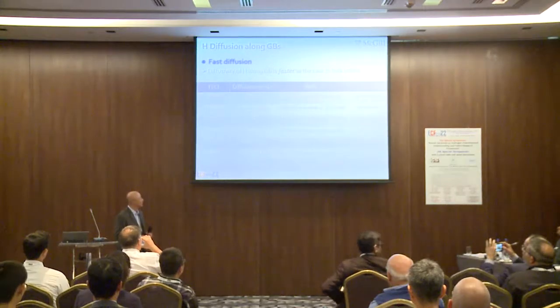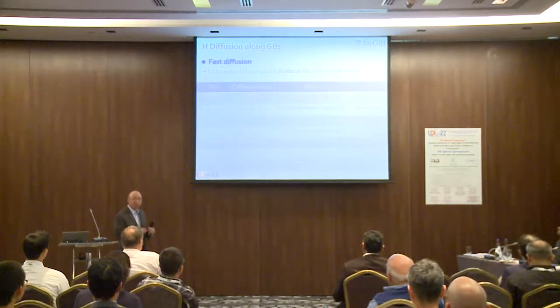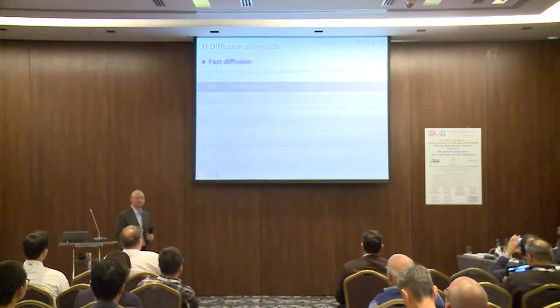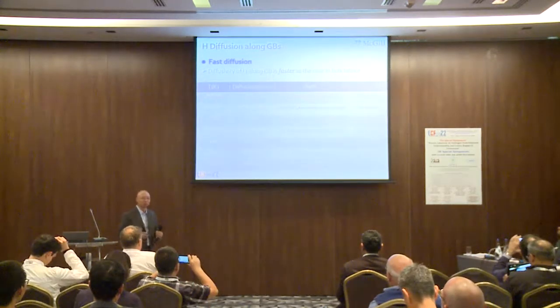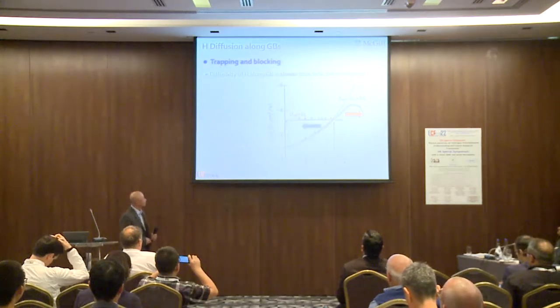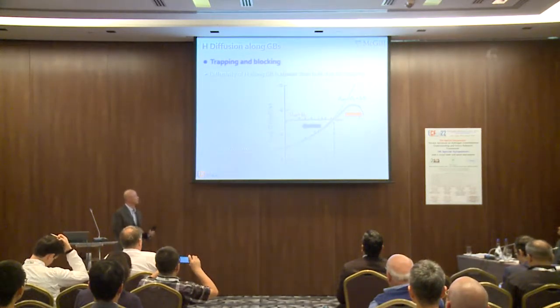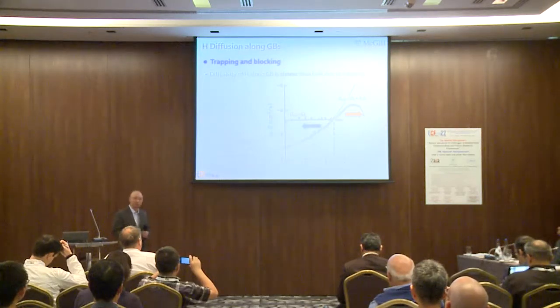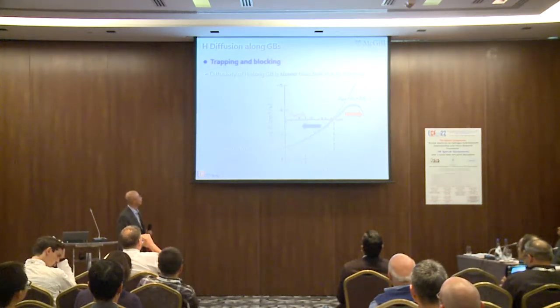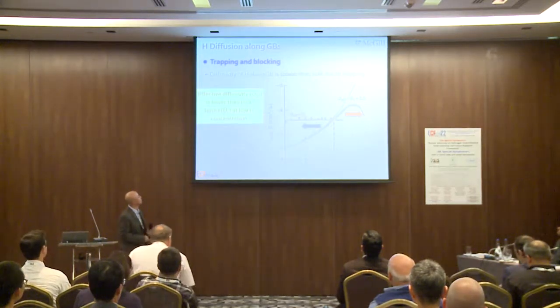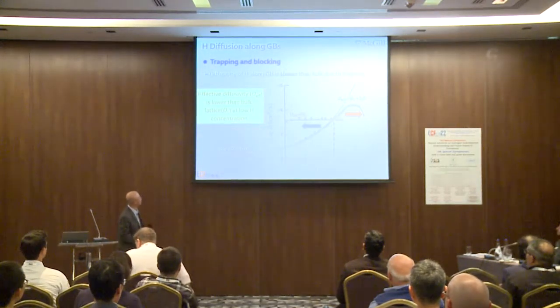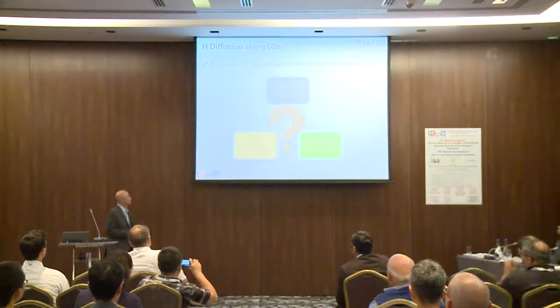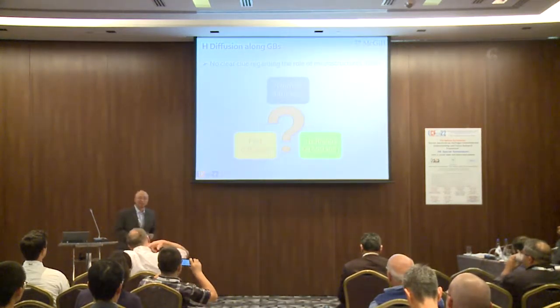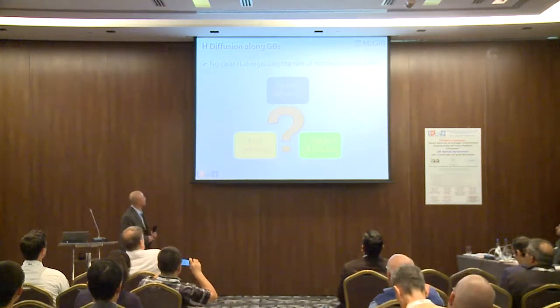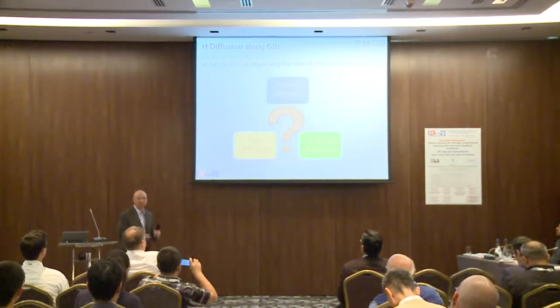There's actually, it really depends on how you measure it, and then you can have different diffusivities, despite trapping or whatever. In contrast, you have other studies saying, and also some data showing, that you can have slow diffusion, particularly at low concentration. Okay, so this is one study. I forgot the reference. Sorry about that. So overall, it's still unknown whether hydrogen diffusion will be faster or slower with the presence of grain boundary.